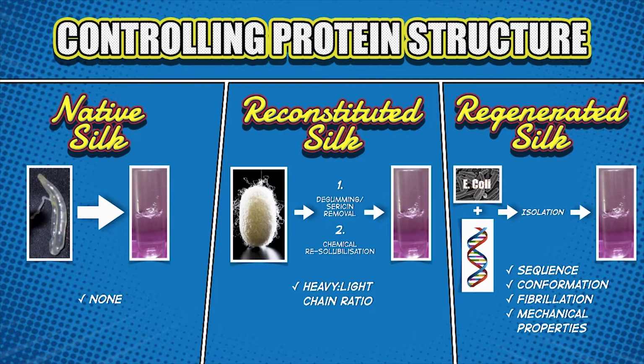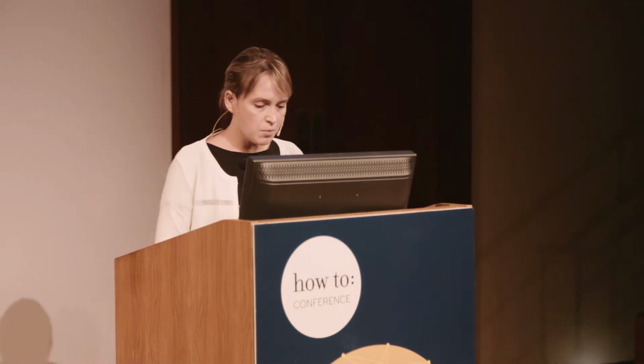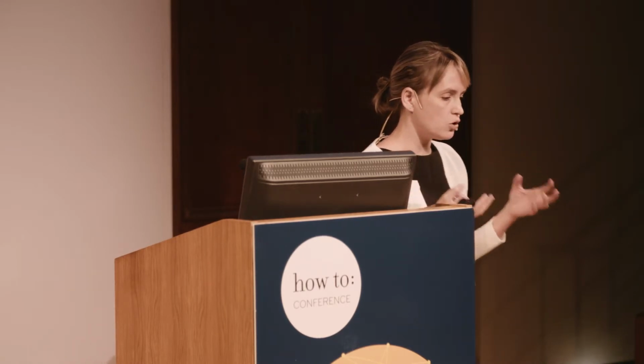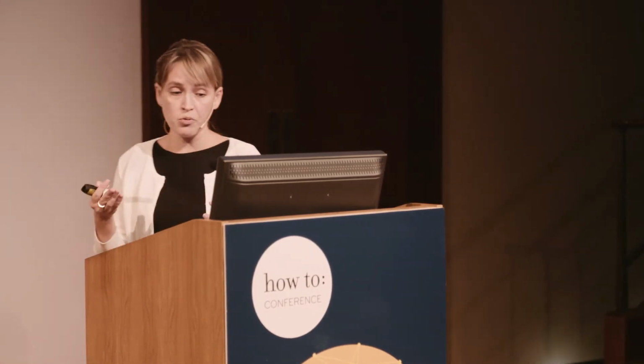Basically, the insect dictates what the final mechanical or pharmaceutical properties of the silk, of the soluble silk, will be. The second type of silk is the same silk that we extract from the silk cocoon by, first of all, unwrapping the cocoon by boiling it in water and detergent, and applying additional chemical resolubilization by boiling the cocoon in strong chemicals like lithium bromide.